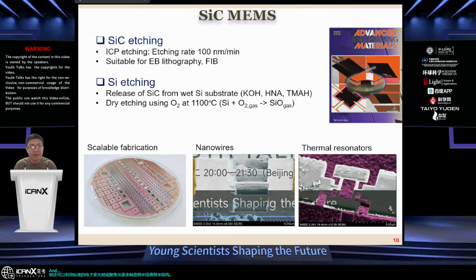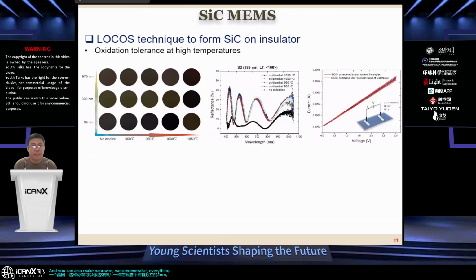And because silicon carbide has very good chemical inertness, you can selectively remove the silicon substrate without attacking the silicon carbide material. You can selectively remove silicon using KOH, HNA, or TMAH, at full scale wafer, so that you can have a freestanding 200 nanometer silicon carbide membrane like this picture. And you can also make nanowire resonators using e-beam lithography.